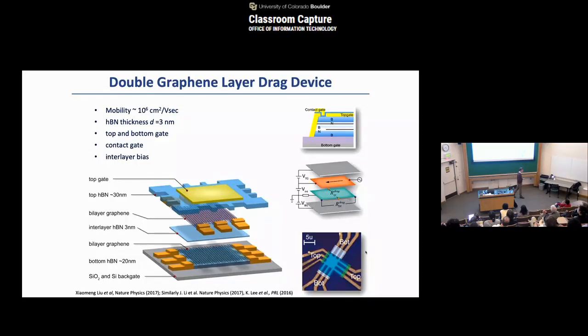Here, as I already mentioned, graphene has a very high quality, like gallium arsenide. Simply, I make these two graphene layers with a separation of boron nitride. I just really copy the experiments and do that. What is the point of doing this experiment, right? There's one important point. Electron is tightly bound again into the graphene layer compared with the gallium arsenide. I just put these two layers very close by, right? Therefore, exciton binding energy is much higher. In fact, the exciton binding energy is almost an order of magnitude, even 2 orders of magnitude higher.